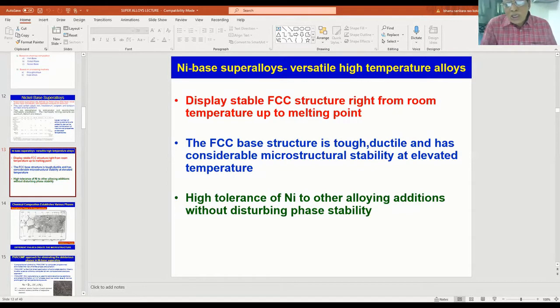Most importantly, nickel has very high tolerance for other alloying elements because of its unfilled 3d shell. So it takes many alloying elements into its fold, into the matrix, without disturbing the phase stability. That is the reason why nickel has been chosen as the base for superalloys in many applications.